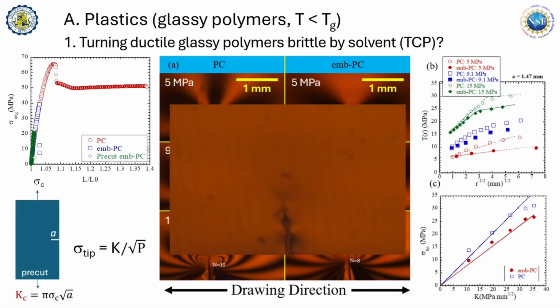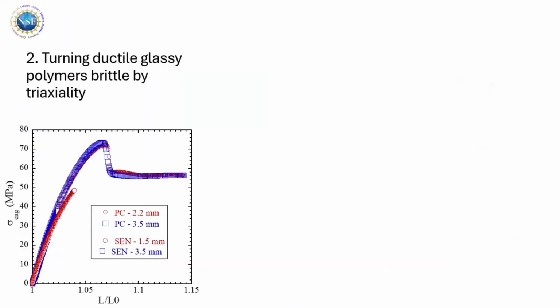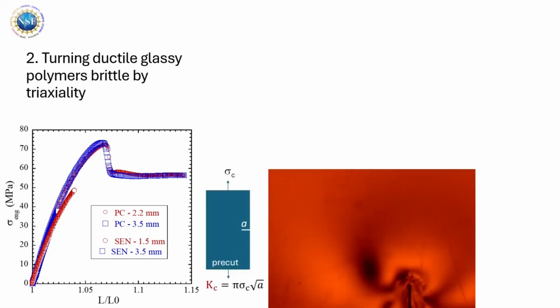So in any event, we were able to resolve the stress at the crack tip and find that stress just grows with the far field load linearly to the point a characteristic length scale pops up. It turns out you can also make a polymer brittle by having your sample thick enough. My theory can explain it, but I don't think I have time to do the theory for you.